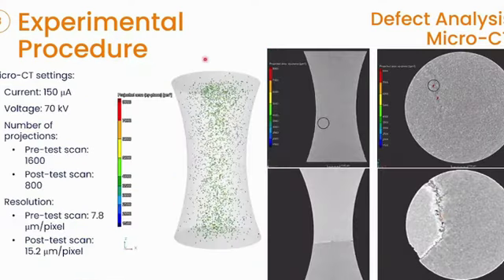So here there is a pre-test scan of a sample showing the defects identified inside the sample. These are the slices, the frontal slice and the cross-section slice, showing the biggest defect that was identified in the failure zone, which is this one here.